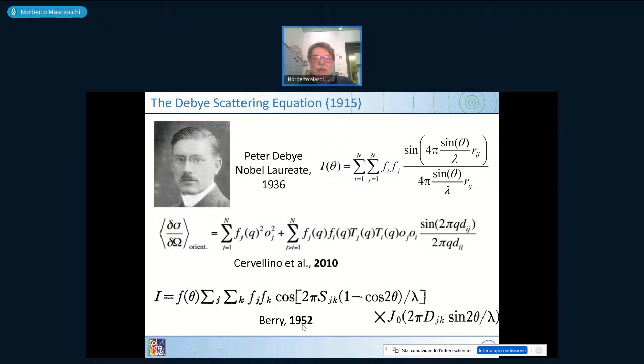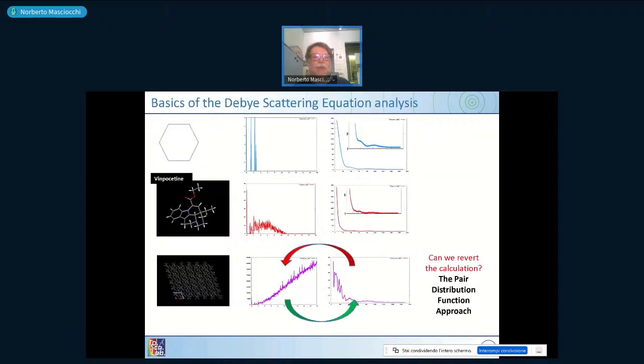So this is a reformulation, which has also included recently a description originally set by Berry but never used for computing because these Bessel functions are difficult to compute manually. In 1952, there were no computers doing this. So the two equations here have now been merged and can give you also the possibility of computing what is called the Debye scattering equation for a textured sample. That means a sample which is not orientationally random. That means that it's giving arcs and not rings if you just have the two-dimensional X-ray powder picture.